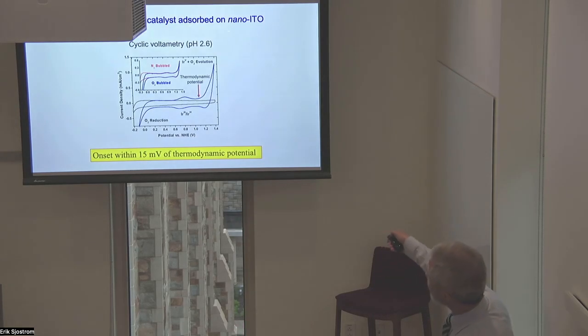So this is now using a conducting metal oxide, nano ITO, or indium tin oxide, which is a conducting oxide. This blue solution catalyst will bind onto the surface, and we can then carry out cyclic voltammetry, in this case at about pH 2.6. And if we carry out a cyclic voltammogram, we see a pre-oxidation, which we attribute to oxidation of iridium-3 to iridium-4, and it's pretty reversible. And then we see the onset of a catalytic wave, which happens essentially right at the thermodynamic potential.